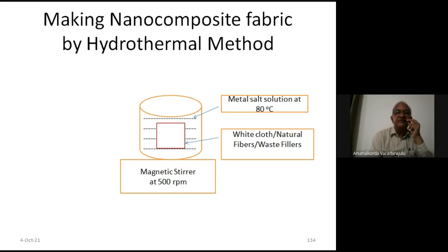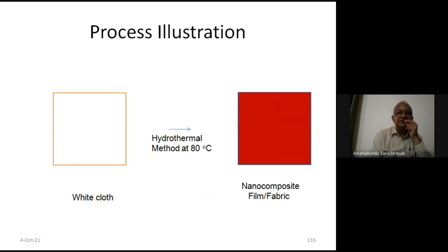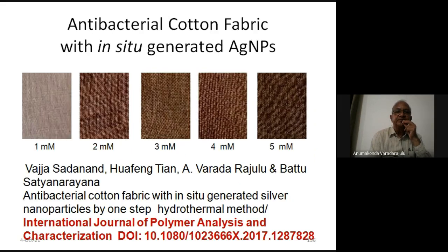Slowly the color of this white fabric changes. The change in color, as I already stated, will be an indication of the generation of the metal nanoparticles inside the matrix. So this is the white cloth, for example. After this hydrothermal process at 80 degrees Celsius, the color of this nanocomposite film or fabric will change. The change in color preliminarily indicates the formation of the nanocomposite.